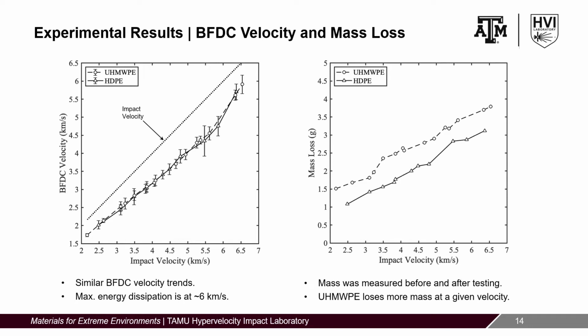If the change in velocity between the incoming projectile and the backface debris cloud serves as a metric for energy dissipation, both polyethylenes dissipate the maximum amount of energy at an impact velocity of approximately 6 km per second. Post-impact forensics were performed on all the specimens to characterize the hypervelocity damage response. Mass loss measurements are plotted as a function of impact velocity on the right.